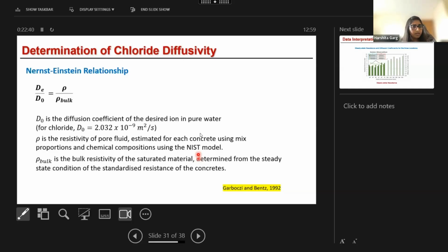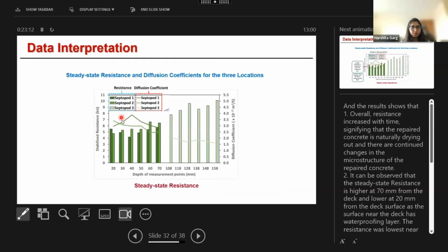Second, we need the resistivity of the pore fluid, which can be taken from the NIST model using the mixed composition and proportion values. Rho bulk is the steady state resistance value that we have got from the analysis, from the algorithm. So that value for all the sensors at different locations was put here. And here we can see the results of diffusion coefficient at 3 locations and steady state resistance at 3 locations.